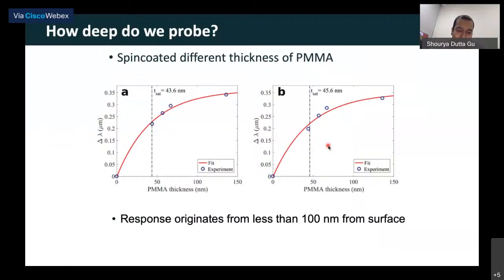Now, you can also verify this experimentally. So here what we are doing is we are using two different metasurfaces with two different sizes. The horizontal axis is the thickness of the PMMA layer, which is the polymer on this metasurface. And the vertical axis is the signal that we are measuring. What we see is as we increase the thickness of PMMA beyond around 100 and 150 nanometers, we don't see a large change in the signal. So what this tells us is even if we make the thickness of PMMA, let's say, 500 nanometers, the signal will still be around 0.35 microns, right? It will not change significantly. And that tells us the typical dimension that we are actually probing, okay?